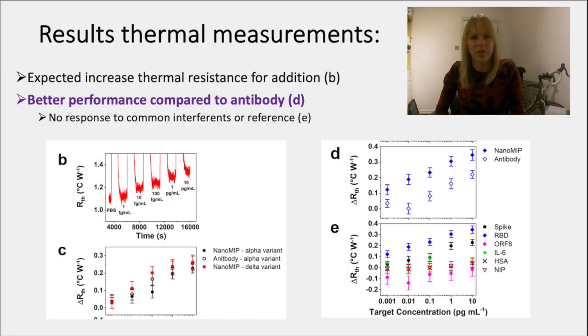Now let's have a look at the measurement results. So what we essentially see is that when you have binding within the material, you start blocking the cavities that you've got on the surface. And when you block it with something which has a lower conductivity, in essence we see both an increase in the electrical resistance, but also in the thermal resistance. And this thermal resistance is what we refer to as RTH.